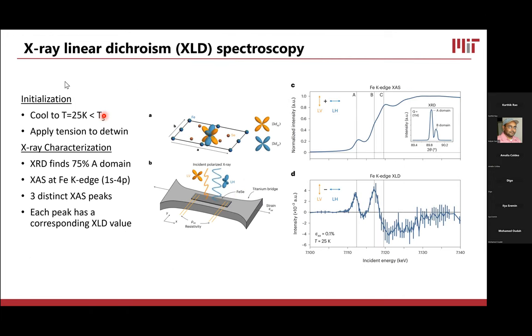All right. So here I'm going to take a sample of iron selenide and glue it to this titanium bridge. There's basically two methodologies for applying strain to samples. You can either glue a sample to a bridge or you can glue a sample over a gap. In this case, iron selenide is relatively soft, and we found that it just worked a lot better by putting it on a titanium bridge. Then we put transport wires on it and we did X-ray measurements on it.